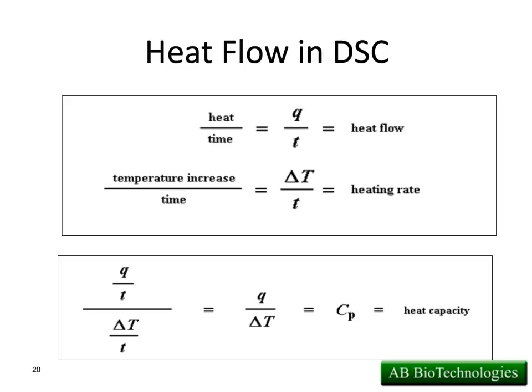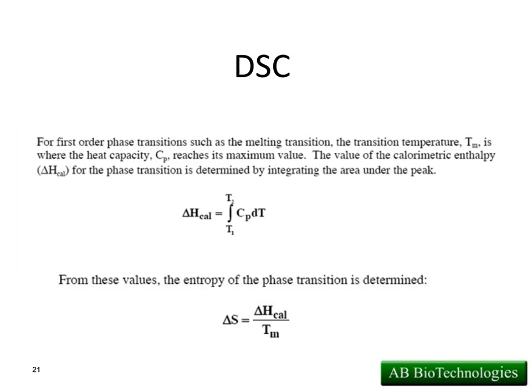Now, what this allows us to do is to start to extract some thermodynamic variables out of our sample. The heat flow, we know, is what the instrument is supplying to the sample. The heating rate is what we control, so we tell the instrument how fast to warm or cool the product. Dividing the heat flow by the heating rate, we get what's known as the heat capacity. This is something very relevant to anybody doing any thermal work, regardless of the industry, for example people working with plastics. We're only scratching the surface of what the DSC can do. By integrating the heat capacity as a function of the temperature, we can extract the enthalpy, or the amount of energy involved in that transition. We can get the entropy of that reaction. A lot of this we're not doing for thermal characterization, but if you're publishing papers or at the university, this becomes extremely important.